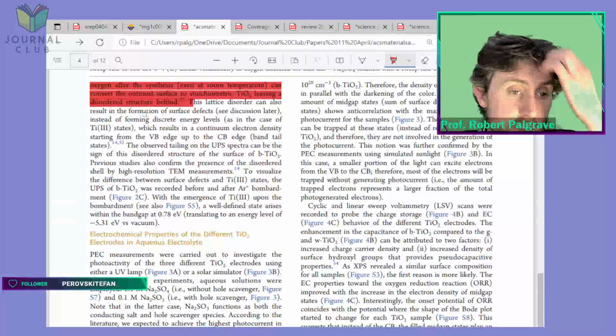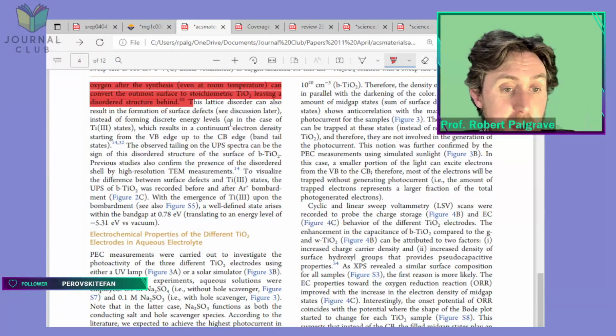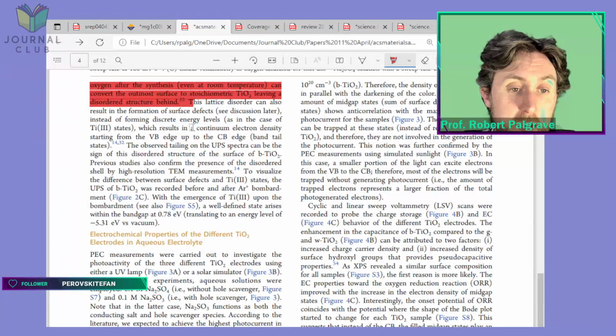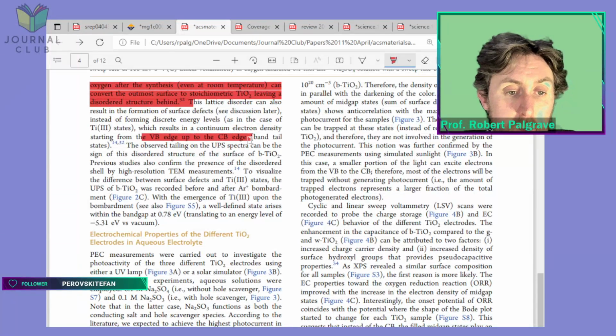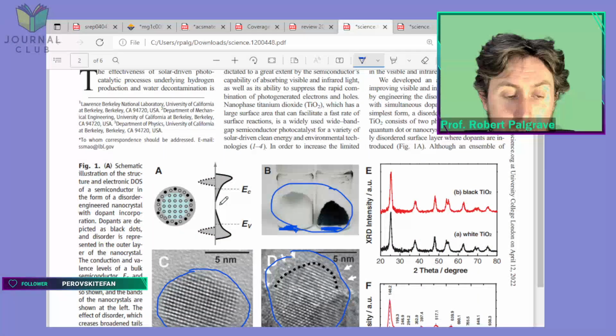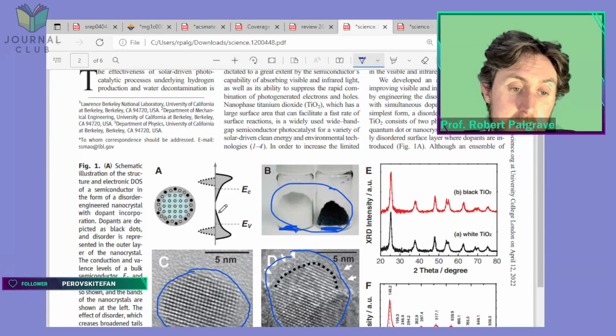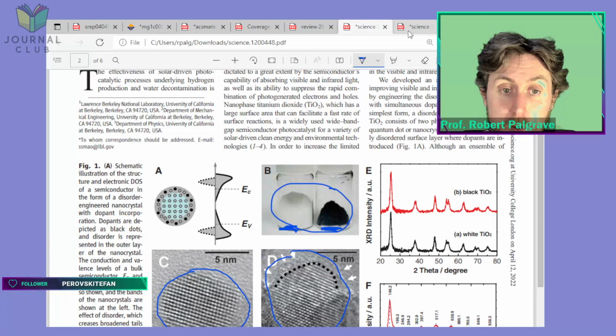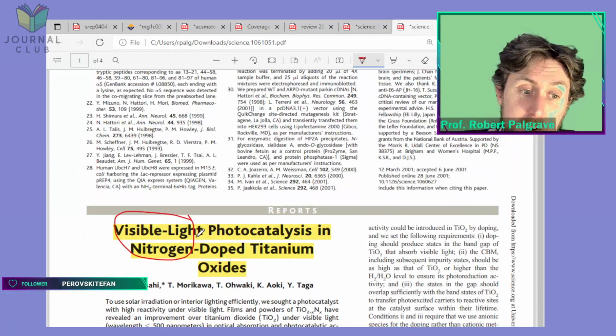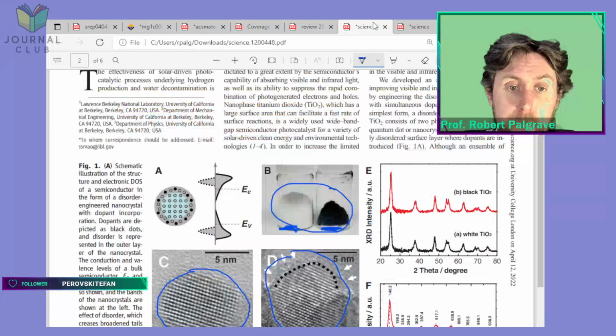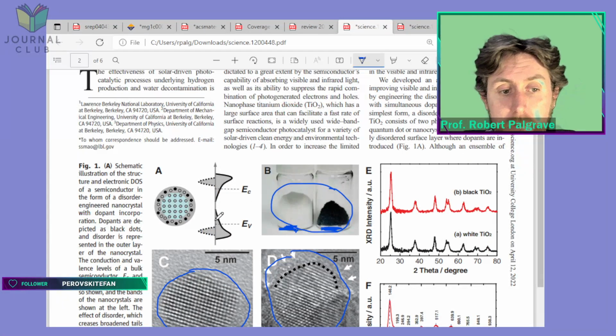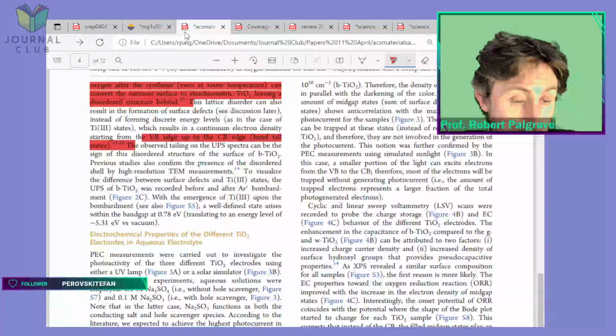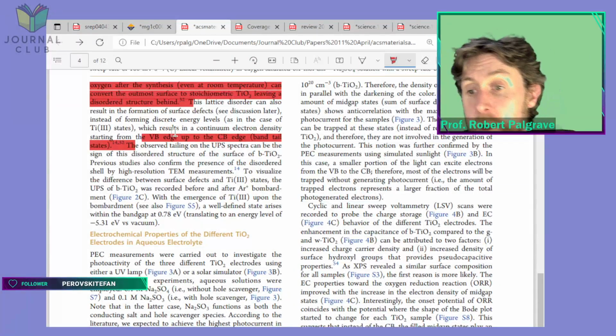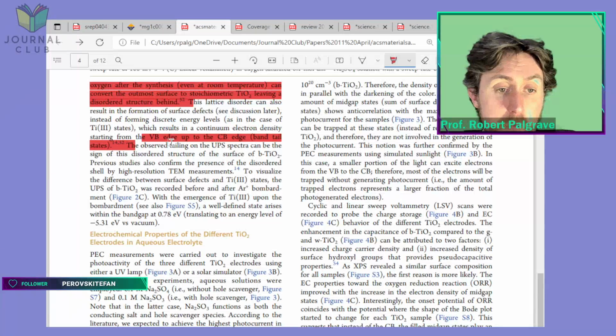This lattice disorder can also result in the formation of surface defects instead of forming discrete energy levels, as in the case of Ti3+ states, which results in a continuum electron density starting from the VB edge up to the conduction band edge, band tail states. Okay, so this is absolutely what they were talking about in the original paper here. The original black TiO2 paper, they talk about these kind of continuum states, not these discrete states, which is actually what you tend to see in, going back to right at the beginning of the stream, the nitrogen doped TiO2. That could be advantageous, that could not be advantageous, depending on the application. But I think it definitely agrees with what was previously observed.